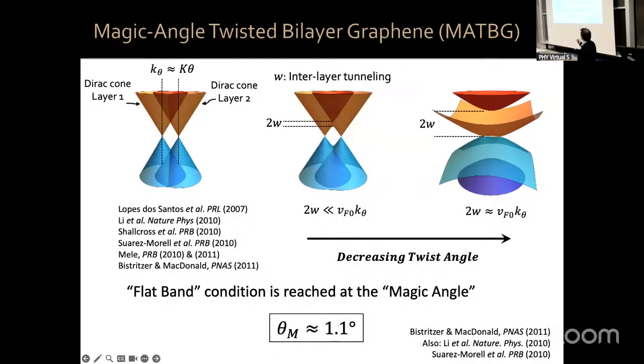Again, it depends on the value of that interlayer tunneling - I'll mention how this can be varied later. I should mention that there was, at about the same time, other theoretical work by Suarez Morell and collaborators, and also experimental work by the group of Eva Andrei, where they used a scanning tunneling microscope. I won't describe the details, but basically these features, where that band repulsion takes place, give you a peak.